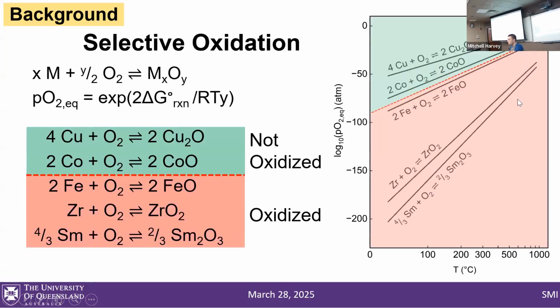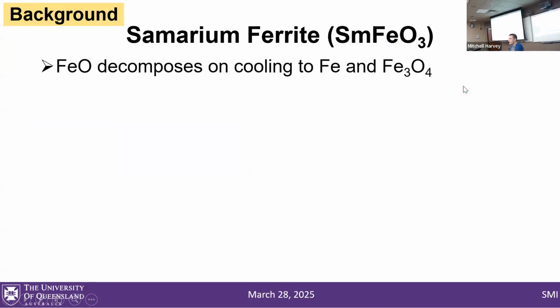So if we go back to the graph, I'm assuming iron plus oxygen goes to iron monoxide. Unfortunately, iron monoxide decomposes on cooling to make iron metal and magnetite. So even if we can oxidize all the iron in the sample at a high temperature, when we cool it back down, a quarter of that iron is going to go back to iron metal. And we don't want that—we want to try to have as low of iron in the cobalt as possible.